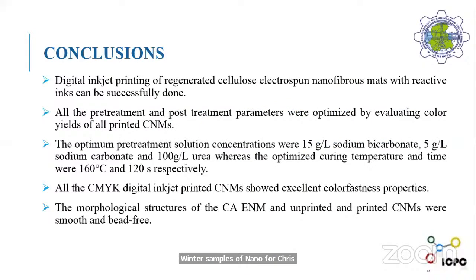Conclusions. Digital inkjet printing of regenerated cellulose electrospun nanofibrous mats with reactive ink can be successfully done for the first time. All the pre-treatment and post-treatment parameters were optimized, and we get the optimum concentration of sodium bicarbonate at 15 grams per liter, sodium carbonate at 5 grams per liter, and urea at 100 grams per liter, whereas the optimized temperature and time were 160 degrees and 120 seconds respectively.